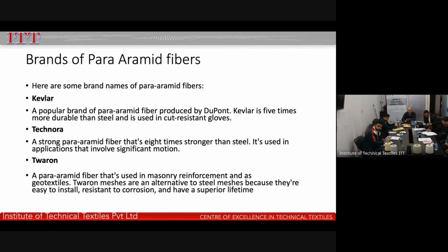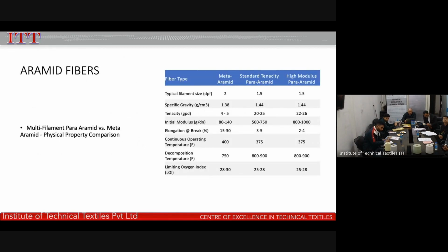The brands of para-aramids are Kevlar. This is by far the most popular brand. Then you have Technora and you have Twaron. Now, if you see the comparison of meta-aramid and the para-aramid fibers, the significant difference comes in the form of tenacity, that is the strength. Meta-aramid is 4 to 5 grams per denier, and para-aramid is 20 to 25 grams per denier.